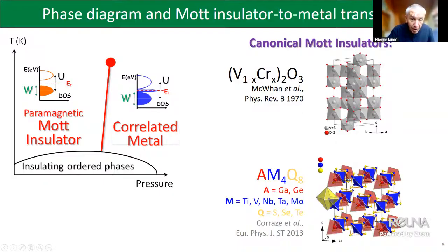Here, the AM4Q8 is a structure which derives from the spinel structure. So it's not 1,2,4, but 1,4,8, as you can see, because there is one site which is empty in this system. But generally speaking, all the effects that I discussed here do not depend on a specific structure. It's really related to the question whether your material is a Mott insulator or not. And if it's a Mott insulator, we can expect the phenomena that I showed and discussed to appear. You see, it's not really related to a specific structure.